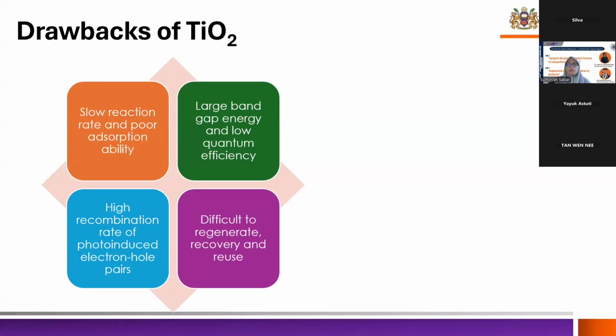So if we want to fully utilize it for solar photocatalysis, then it's not very good because there is only about 5% of UV in our solar. So we need to shift the activity of the titanium dioxide towards the visible light region. And it has a high recombination rate of photo-induced electron-hole pairs. So in this case, if the excited electron tends to recombine back with the positive holes, then it will slow down the reaction because the electron cannot participate in the reduction reaction or oxidation reaction.